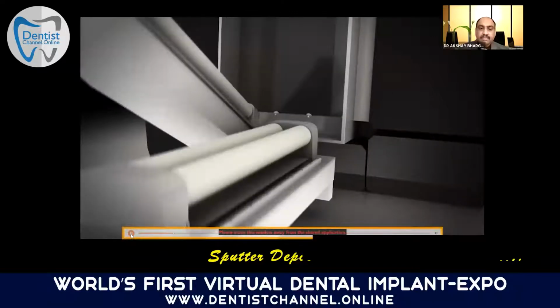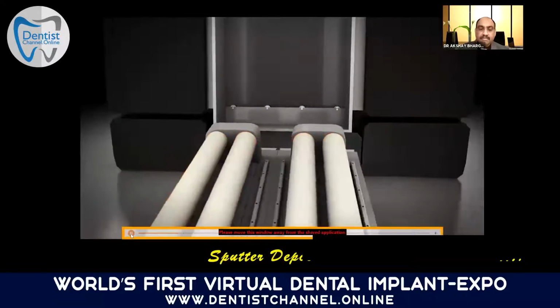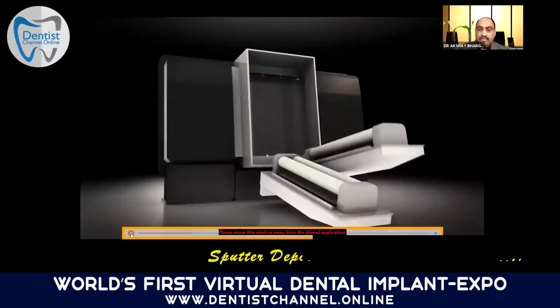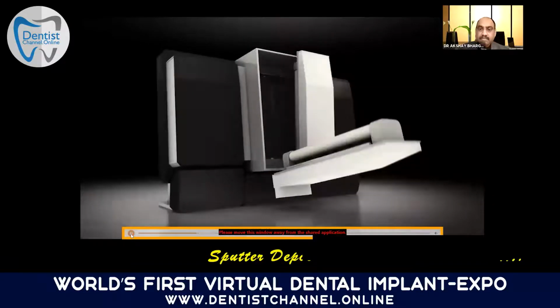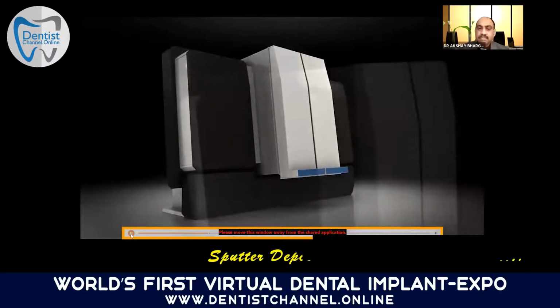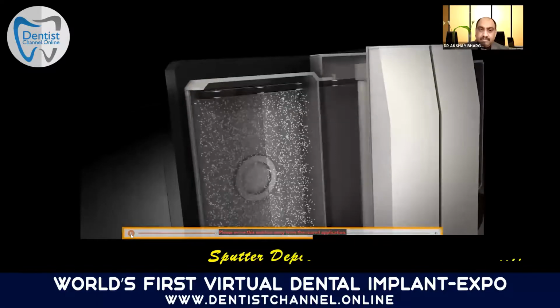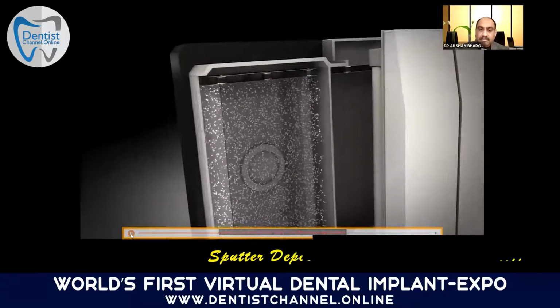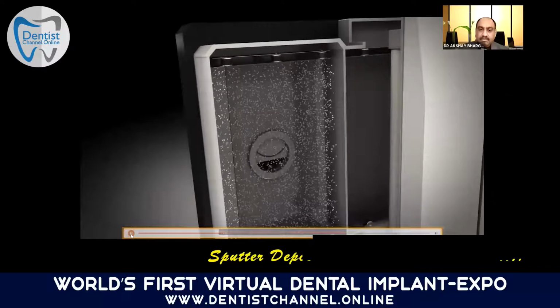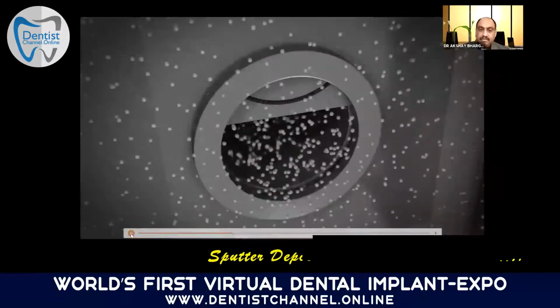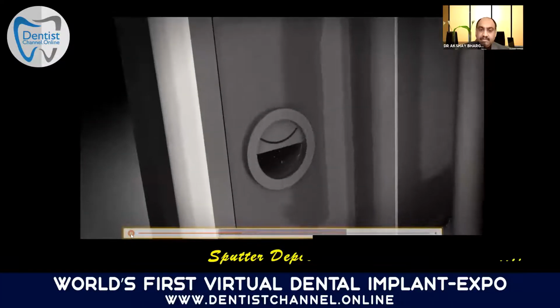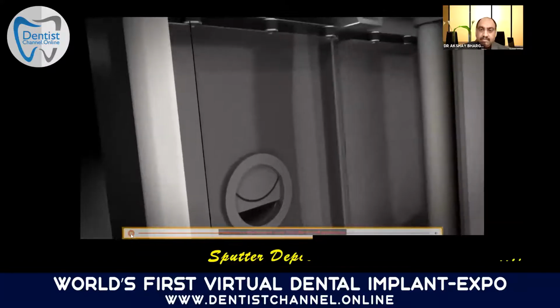The source of the thin film material is a planar or rotary sputtering target of metal, ceramic, or even plastic. Molybdenum targets, for example, are used to produce conductive thin films in displays or thin film solar cells. At this point, the process starts. Air is continuously removed by vacuum pumps. The base pressure in the vacuum is around 10 to the minus 6 millibar, which equals about a billionth of the atmospheric pressure.